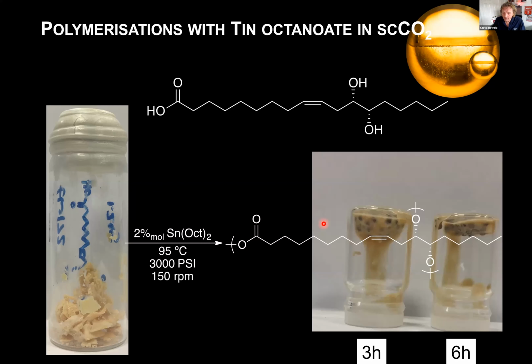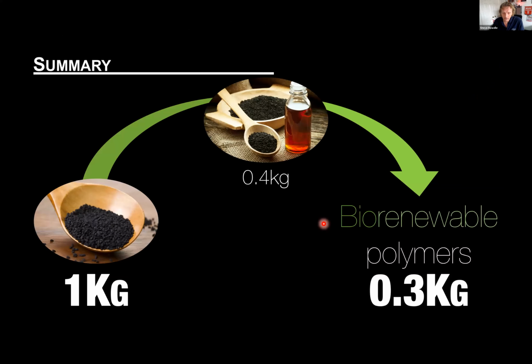So this is just 2 examples of degradable polymers that we can produce from natural resources, where we use CO2 to do the extraction and also to do the reaction solvent. And so we've got some really good news here, because you could take 1 kilogram of seeds, you could extract up to 400 grams of the oil, and then with a bit of chemistry, we can turn them into monomers, and we can end up with about 300 grams of polymer. So it seems quite a reasonable process.